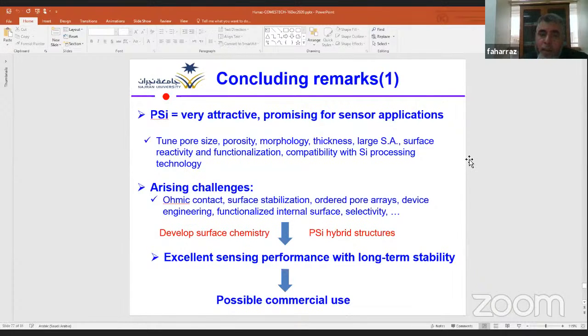However, some challenges in the utilization of porous silicon in sensor application are still there, including creation of good and efficient ohmic contact, how to make surface stabilization of the device, and how to get ordered pore arrays in device engineering. If we develop some surface chemistry and fabricate some hybrid structure, we might be able to get excellent sensing performance with long-term stability, which will in turn help for possible commercial use.